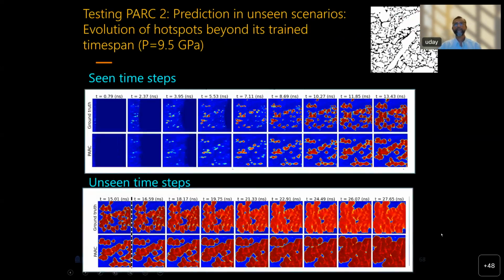The second thing we tested was looking at time evolution beyond training. That is, we train Park for a certain time and then we let Park go. And then we do the DNS for those longer times and see if it captures the evolution correctly beyond the training time, which is an extrapolation. And Park does that successfully.